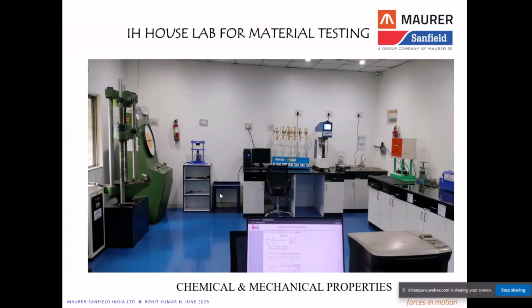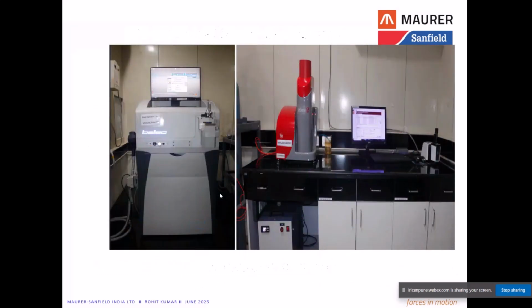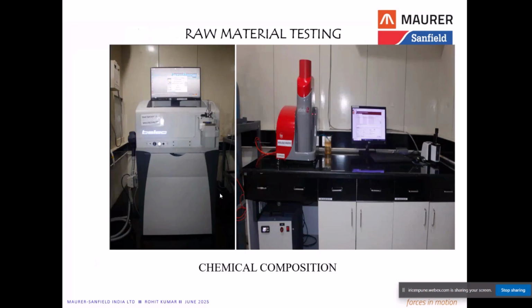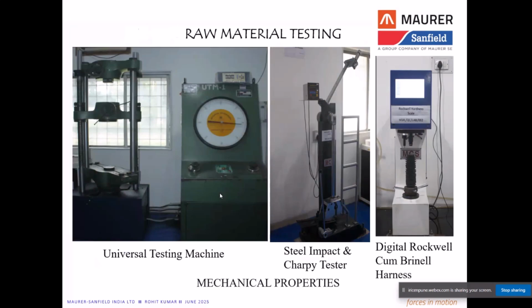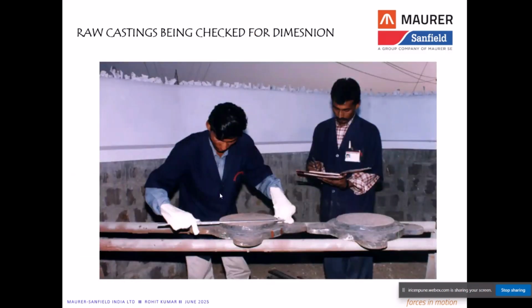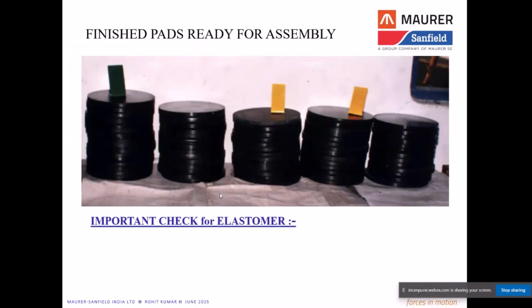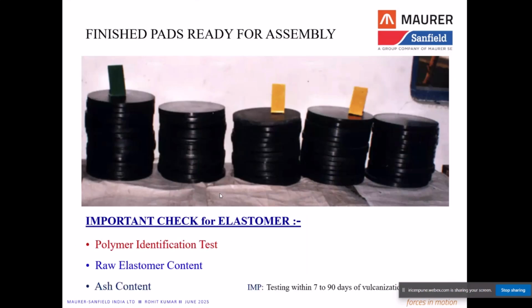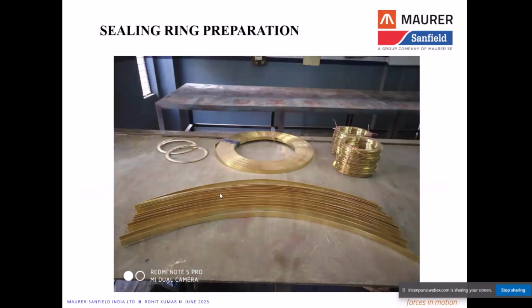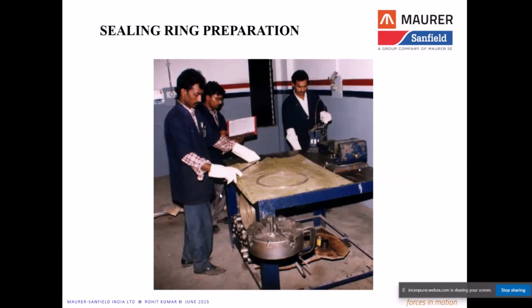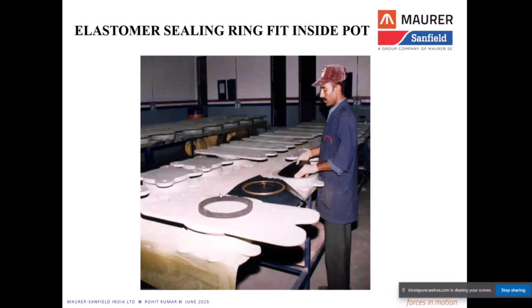For that, it is necessary to check the raw material in both ways, chemically and mechanically, using different equipment or machinery available in the market to check all the chemical composition as well as the mechanical properties of the raw material. These machines give an idea of the raw material which has been used for manufacturing these bearings. After that, there is a requirement to check the component dimensions properly before starting the production of these bearings, and to check the soundness of the cast or steel material, whether it is fulfilling the requirements or not. If all these things are completely checked before being used in production of the bearing, about 70% of the chances responsible for failure of this kind of bearing are removed.